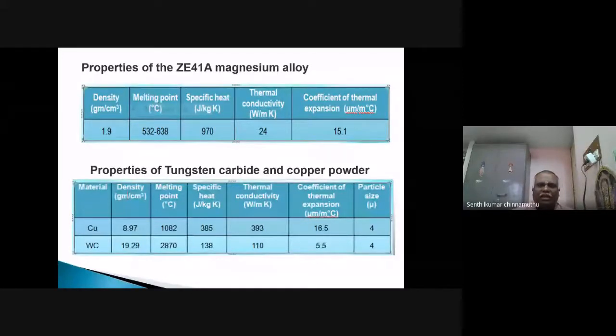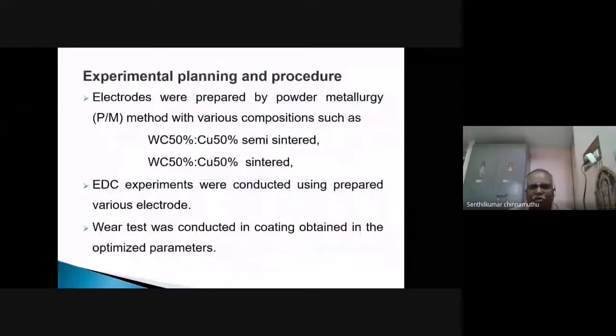The experimental planning and procedure: electrodes were prepared by powder metallurgical method of the combination of 50-50%, that is tungsten carbide 50%, copper 50%, semi-sintered and sintered. Two types of electrodes were used, semi-sintered and sintered. We have to compare both the tools to evaluate the deposit layer, the characteristics of the deposit layer, how much quantity of material is deposited using semi-sintered and sintered. What are all the mechanisms? We have to evaluate that.